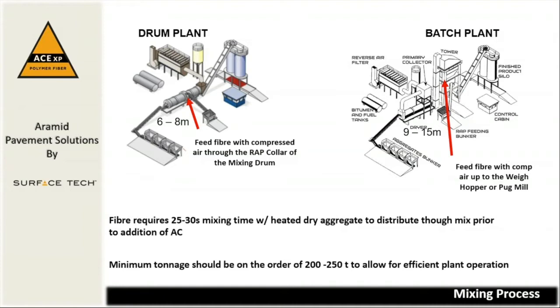The key requirement is that we have 25 to 30 seconds of mixing time with the heated aggregate prior to the addition of asphalt cement in order to strip the wax and allow for the interaction of the Aramid with the aggregate.